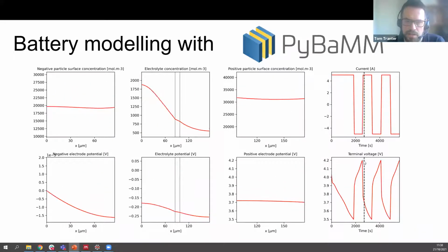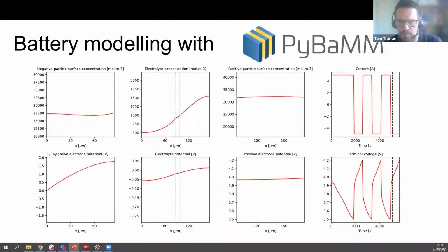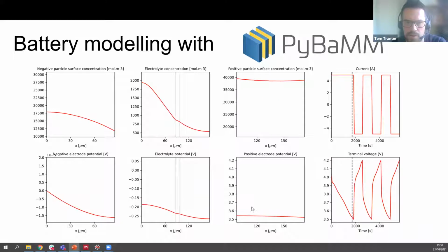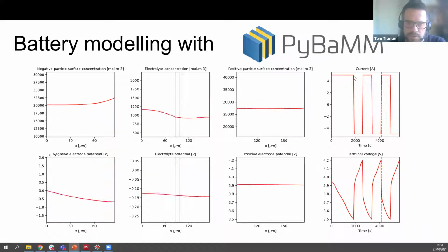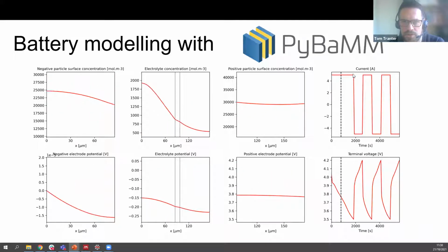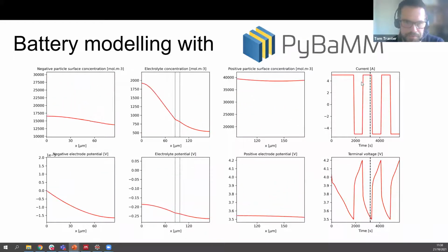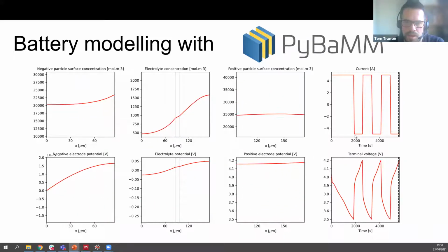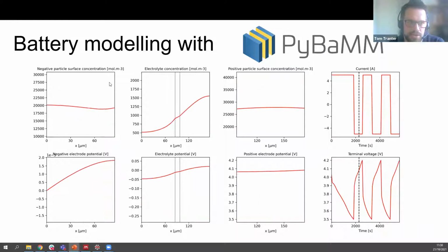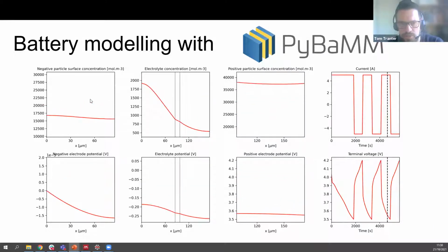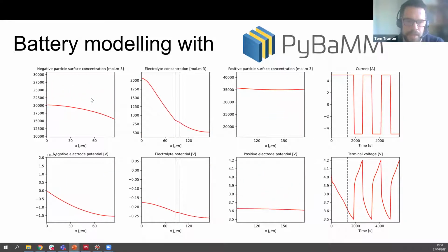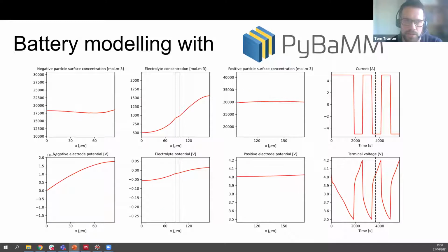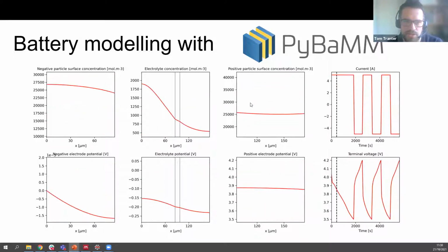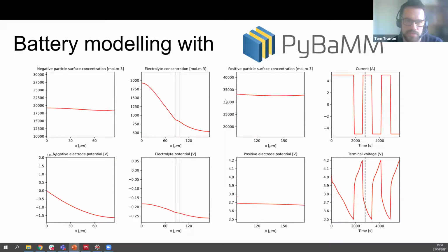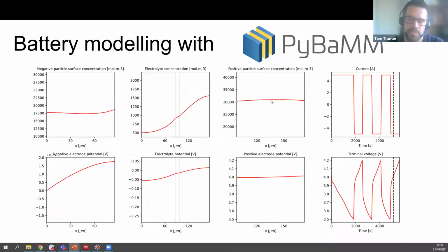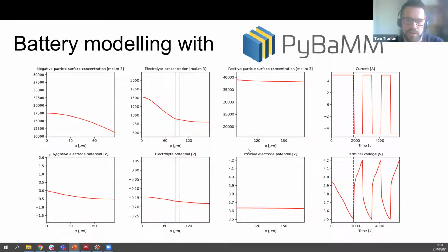And typically when you look at a cell and you want to know any sort of information about its state of charge or state of health, you'd look at the voltage and you'd do Coulomb counting on the current, which essentially just means that you're measuring the current over time and counting up how much charge must have passed back and forth. With the modeling, you can get more details. And with this change in particle concentration, you're changing the properties of the materials. So you're changing the density and also the Young's modulus, and that's going to affect the acoustic response. And what we actually see as we charge and discharge, we have this seesaw of ions going back and forth. We can actually detect that with acoustics, even though the length scales are very small.